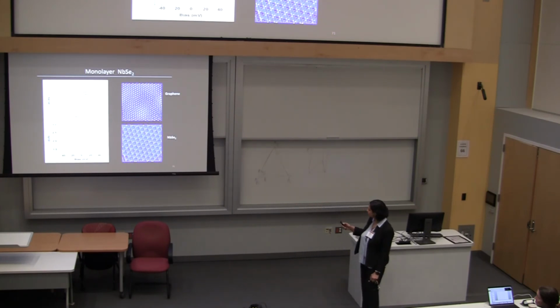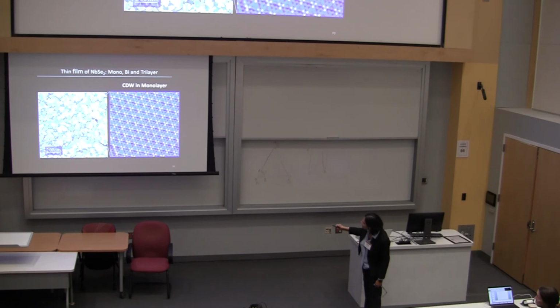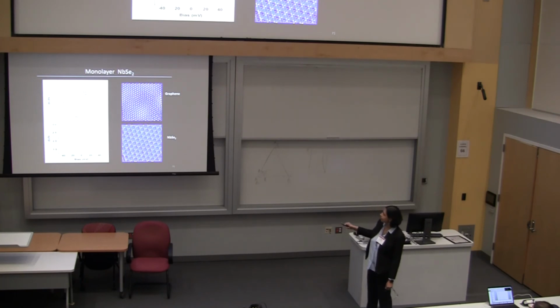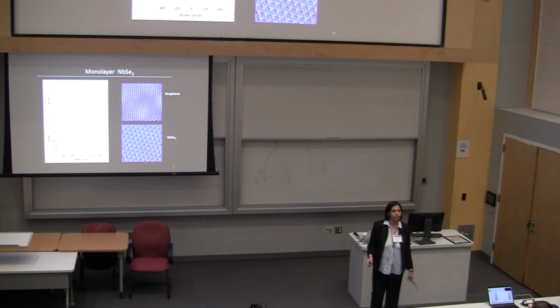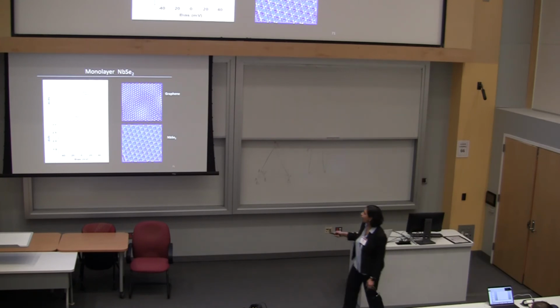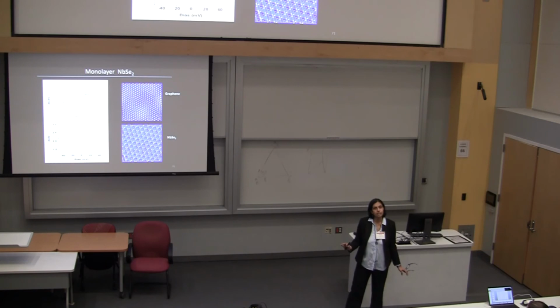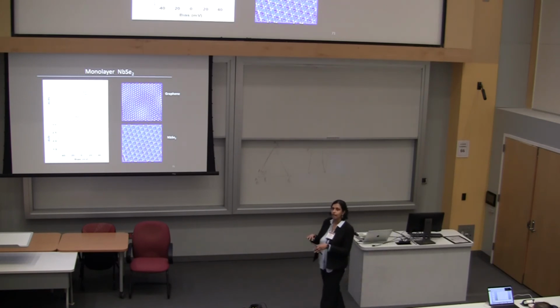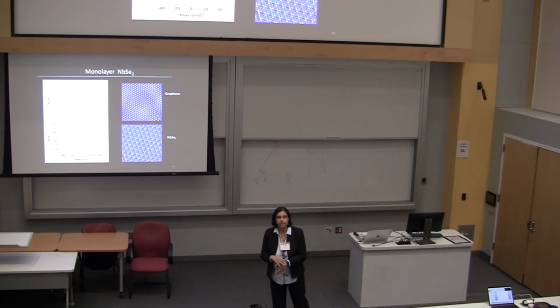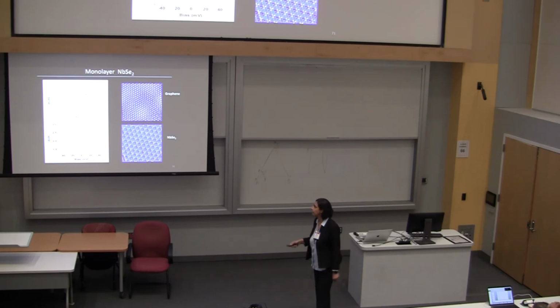Now, if you look here, you can see areas of graphene. Those are the dark areas, right? That's graphene. If you go to graphene and measure the density of states, it looks like this, which is sort of expected for graphene. It's sort of V-shaped. However, if you go on niobium diselenide and you measure the density of states, it looks like this. It's completely different. So basically, this tells you that the niobium diselenide is pretty seriously decoupled from the graphene underneath.